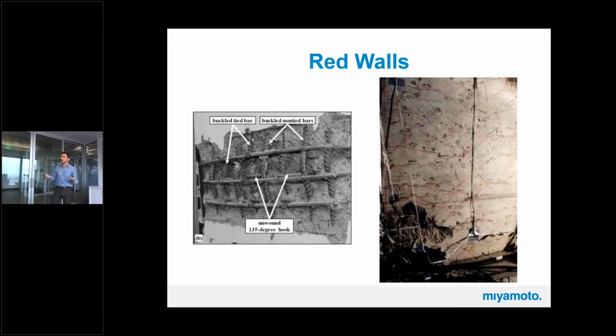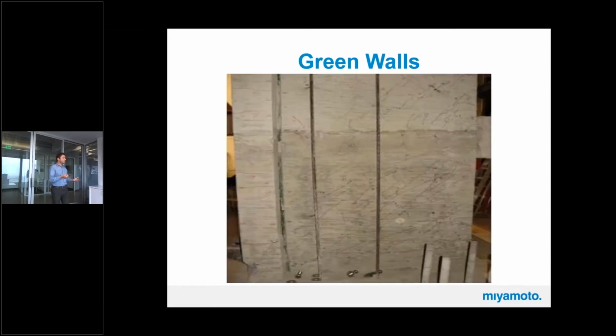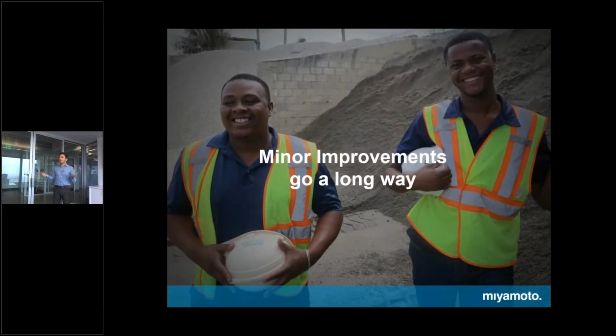Okay, spalling, crushing in concrete, followed by buckling of the reinforcement, and huge cracks in the bottom and mainly in the boundary elements. And the green ones, definitely the reinforcing yields, you would have cracks, but not major cracks. They would be like normal cracks along the wall. So we have the location of the damage and we know what happens to the shear wall.